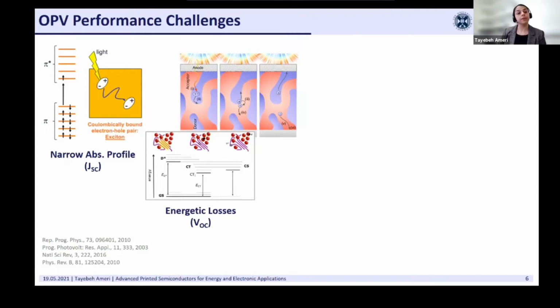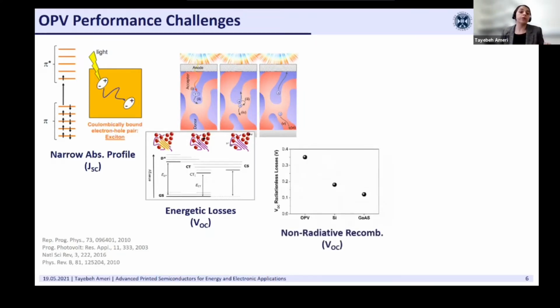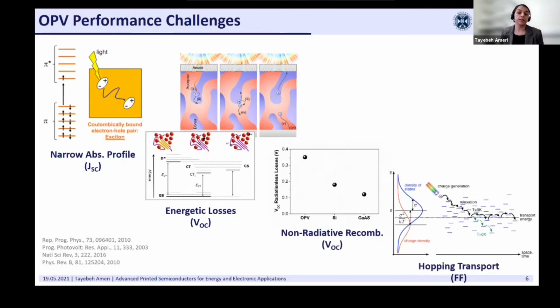And this class of materials, organic materials, are kind of soft and amorphous materials. So they are trap dominant, and there is a lot of non-radiative recombination that, as you see here, is reducing the open circuit voltage 2 to 4 times more than other technologies like silicon or gallium arsenide. And finally, the charge transport in this class of materials is based on the hopping process and very electric field dependent, and it limits the fill factor in our devices.